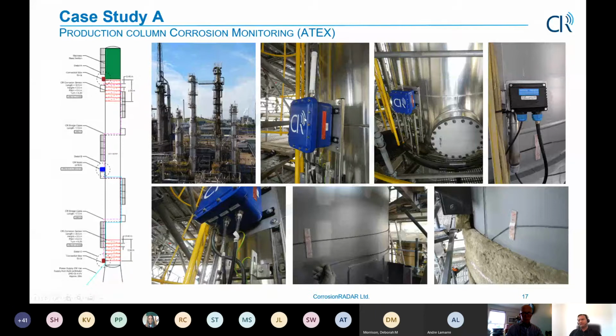The electronics is zone 1 in ATEX. The wireless transmission is using a cellular network in this case, and you can see the 2 channels here. Now, in this case, the asset was sandblasted, painted, and refurbished, but still there was a need for this monitoring system because the trust in the coatings was not high. In the past, this asset had coatings, but even then it developed CUI. So that's an example that even if you have a preventive measure, a monitoring system is needed as an assurance tool, to ensure there's no water in and no corrosion developing on the sensors, which would indicate the risk to the assets.